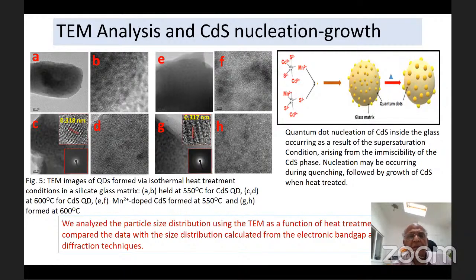So we analyzed the particle size distribution using the TEM technique as a function of heat treatment and compared this data with the size distribution calculated from the band gap and X-ray diffraction technique. We also then concluded from that quantum dot nucleation of CdS inside the glass is occurring as a result of the supersaturation condition, arising from the immiscibility of the CdS phase in the silicate glass. Nucleation may be occurring during quenching, followed by the growth of CdS when heat treated.